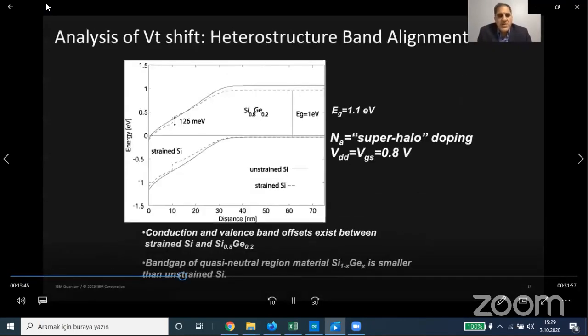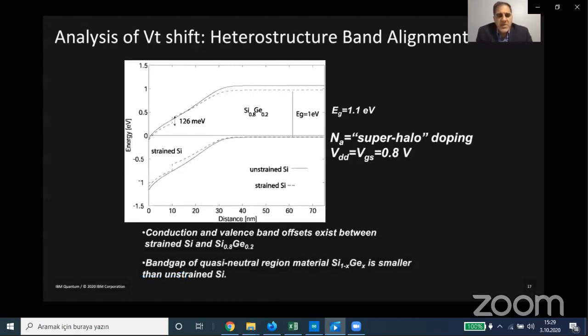In addition to the mobility model, the band offsets were modeled very carefully here. Here I introduced the band offsets in the heterostructure. At the top layer is the strained silicon. You can see the silicon germanium. So for the same gate voltage, due to the band offset here in the conduction band, there are actually more inversion electrons at the surface when strained. So the VT is lower for the strained silicon.